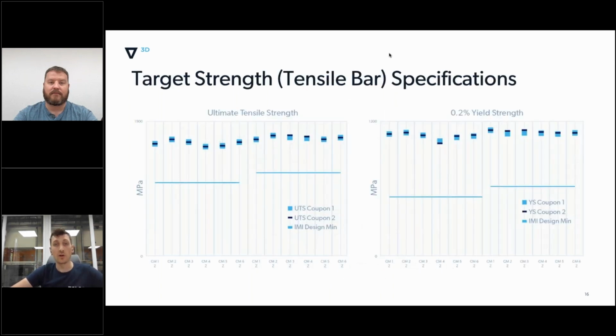So next, of course, we also looked again at the witness specimen, the tensile bars. And first of all, all of them were well above the IMI design allowable that was specified for the ultimate tensile strength as well as the yield strength. But what is even more astounding to me is that, basically within, I want to say, plus minus 50 megapascals, we were able to achieve consistent mechanical properties on all of these parts. So what does this mean, or what did these results ultimately prove?